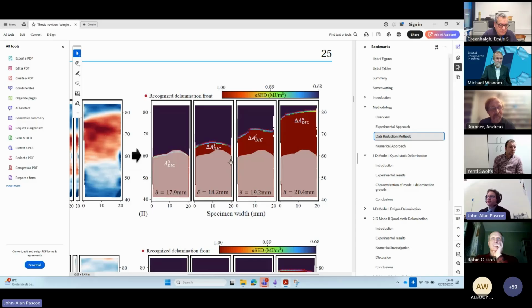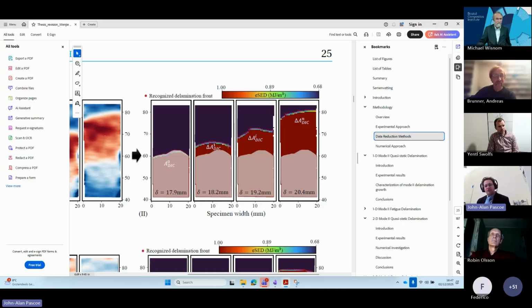So you can see the strain distribution across the top of the specimen. And this is also from Vinji's thesis. And he then processed it to an equivalent strain energy density. And then the idea is that this gradient shows you where the crack front is. So we can argue about the exact value of where we determine the crack front, but the main point is that this crack front is not straight. Which also suggests that if you make your specimen wider or narrower, then you have more or less influence of the edge effects, which would then influence whatever value you're trying to extract from this with the classical data reduction schemes, which do not take this into account.